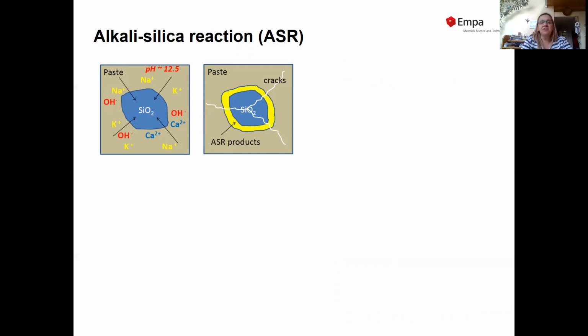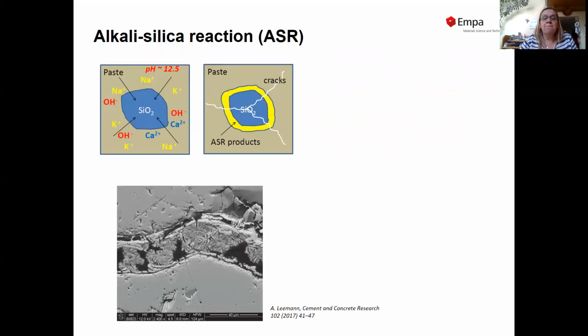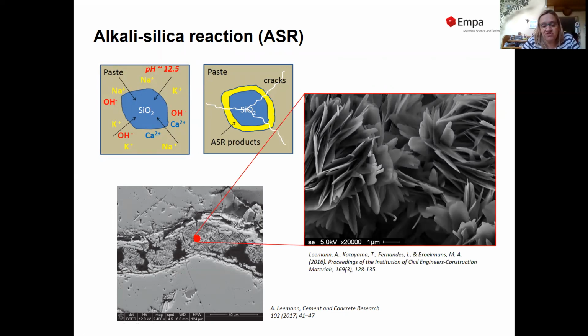I now come to the last of my topics. It's alkali-silica reaction. Alkali-silica reaction occurs in concrete, mainly due to the reaction of the silica with high alkalis from the pore solution and the calcium. It leads to cracking and expansion. And we also can see then the formation of this ASR product within the aggregate. It can be crystalline or amorphous. I have shown here an example of a crystalline sample, which has been pictured by one of my colleagues.